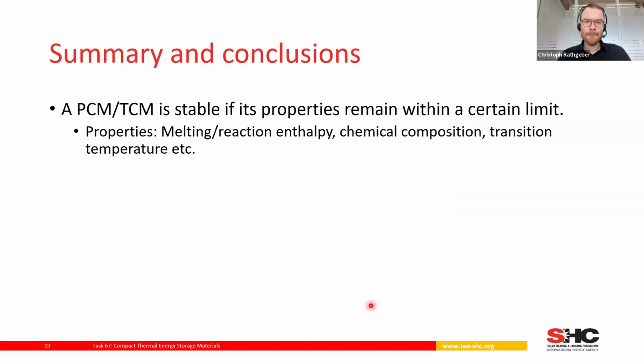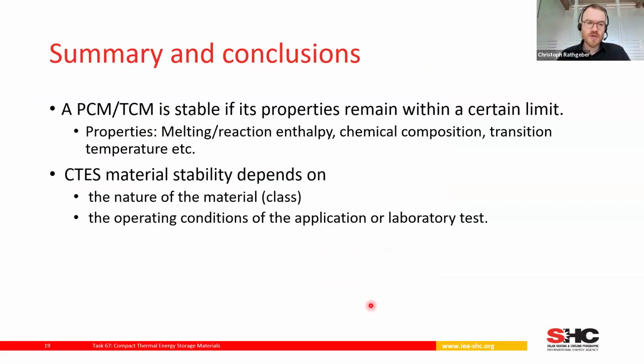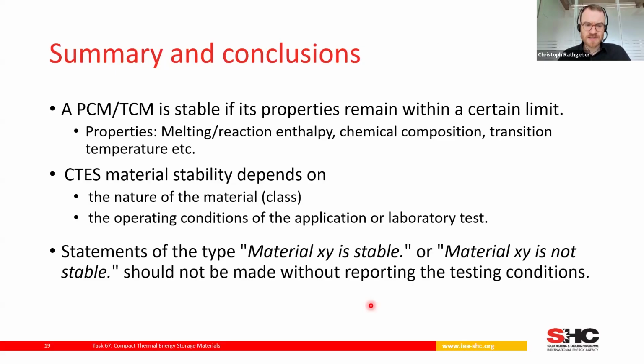So to summarize and conclude, or maybe to start with the definition at the beginning, we can say that PCM and TCM are stable if their properties remain within a certain limit. So properties of interest are, as you see here, melting and reaction enthalpy, chemical composition, transition temperature, and so on. The material stability of PCM and TCM highly depends on the nature of the material, so the material class, and also, of course, on the operating conditions of the application or the applied laboratory testing. And that means that general statements of the type 'material whatsoever is stable' or 'the material is not stable' should not be made without reporting the testing conditions.